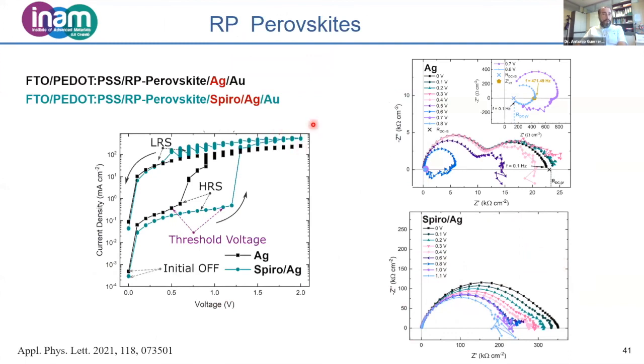Okay, we've used this knowledge recently to make memristors. And here we have the response of 2 different memristors made with RP perovskites, using PEDOT:PSS and silver as a reactive interface with the perovskite, and a spiro layer as a layer that lets the ions go through.